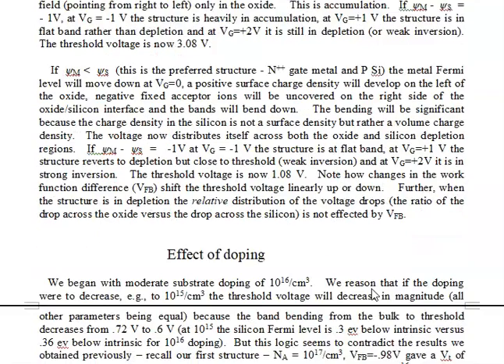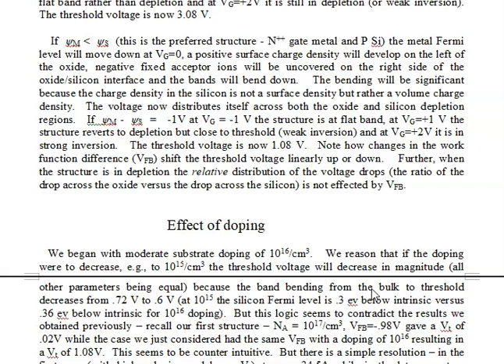Okay, let's go on to the effect of doping. The first example, everything we've done in this previous part of the section, had a doping density of 10 to the 16th for the P silicon. Now we can reason that if the doping were to decrease, and we're going to do that in just a little bit, to 10 to the 15th, our reasoning is that the threshold voltage will decrease in magnitude, all of the parameters being equal. That's important, because at a lower doping, the intrinsic level is closer to the Fermi level. The Fermi level is higher up, and the closer the Fermi level comes to intrinsic, the easier it is to push it over to the other side.